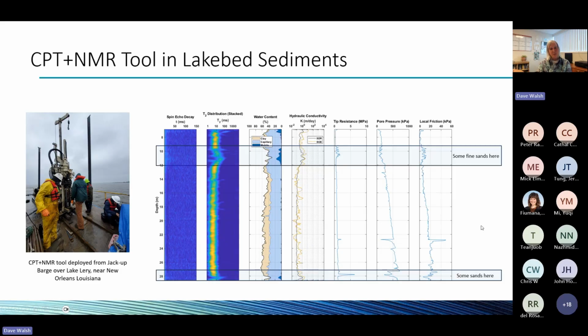A second example is using this tool from a jack-up barge over a lake near New Orleans, Louisiana. In this case, we got very soft lake bed sediments. Not terribly interesting, these curves. It's very soft, not much resistance, not much friction, except for where you have some sands mixed in here and there. But with the NMR data, you also get total porosity and total water content.